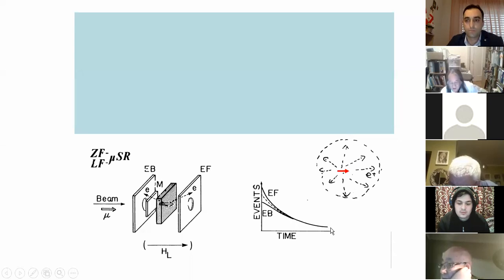Okay, however, one positron is emitted from one muon, but the probability that the positron is emitted has a correlation with muon spin. So if muon spin is keeping its polarization, then you have more positrons expected to come towards this forward direction as compared to the backward direction. Then what you will have in this histogram is that you will see this asymmetry of counting rate. Forward is more than the backward.